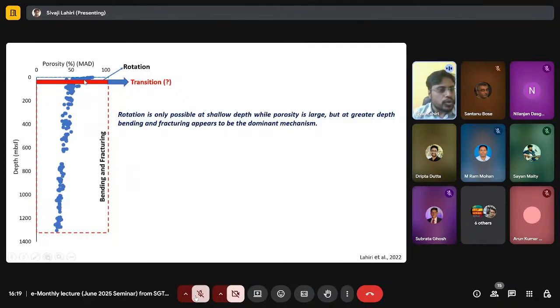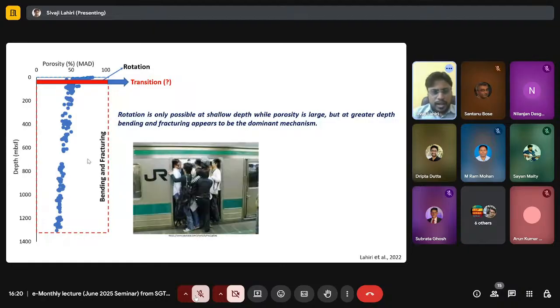Initially at the shallow depth from seafloor to 30 meter, samples had lots of pore or vacant spaces within them. So particles can easily afford rotation. However, at greater depth, from 30 meter to 1300 meter, samples did not have enough pore or vacant spaces surrounding them. So particles could not afford rotation. So particles got deformed by bending and subsequently fracturing. I think you can also do a very small experiment using the pen which is there in your hand. Try to rotate your pen, you will find that you actually need larger vacant spaces surrounding it. But when you are trying to bend the pen, you need actually smaller space, which is happening here in these particular samples. Now, a similar kind of thing we also observe in our day-to-day life.